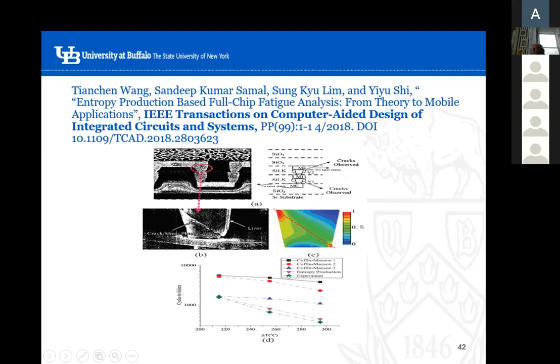So they have the experimental data, the green one, and then they have this purple one that they call entropy production, calculated using unified mechanics theory. And then these are from Coffin-Manson data. You know, Coffin-Manson data is obtained from an experiment, and then you use those coefficients for a real system. So you can see that the entropy production gives almost identical results as the experiment, but Coffin-Manson is far, far off.